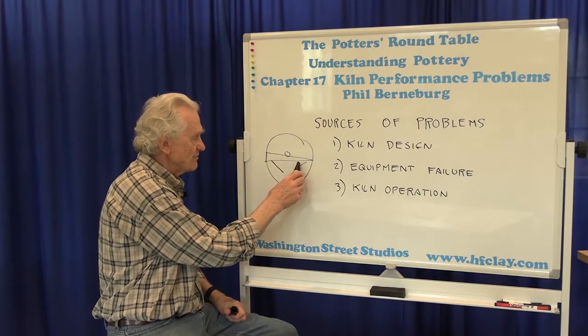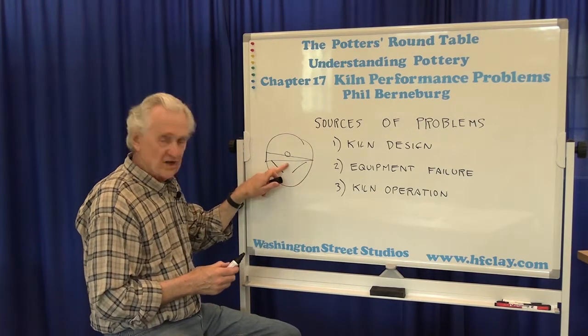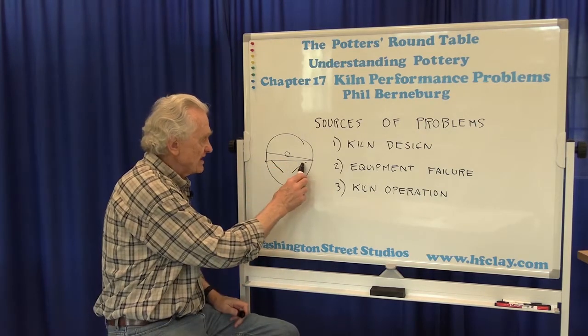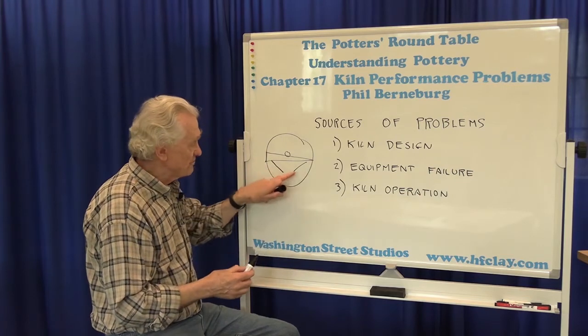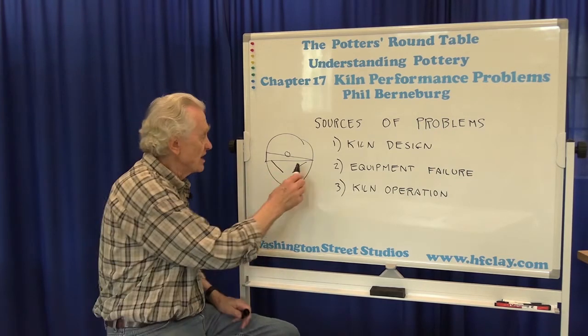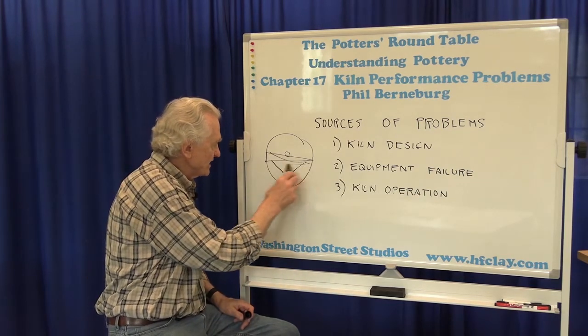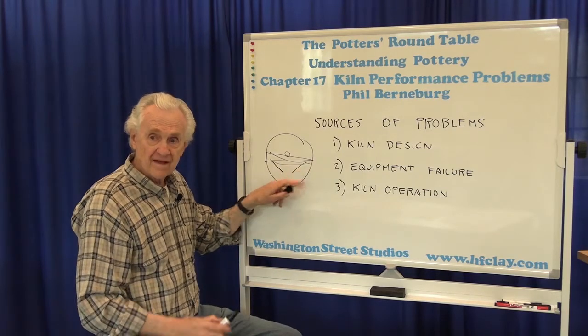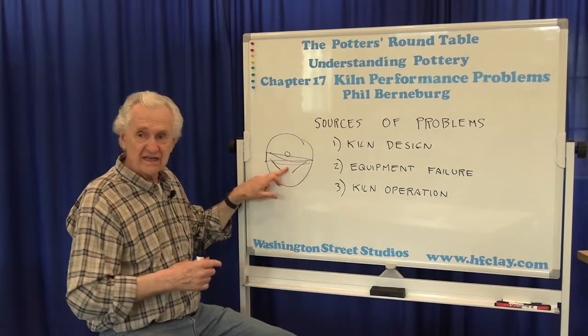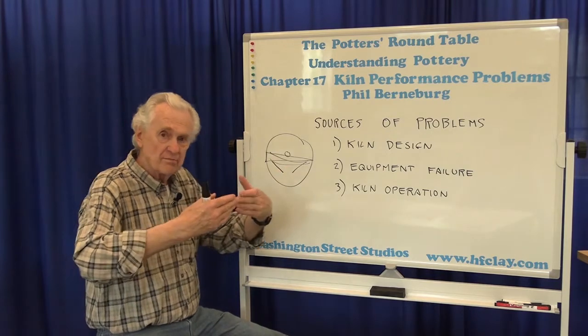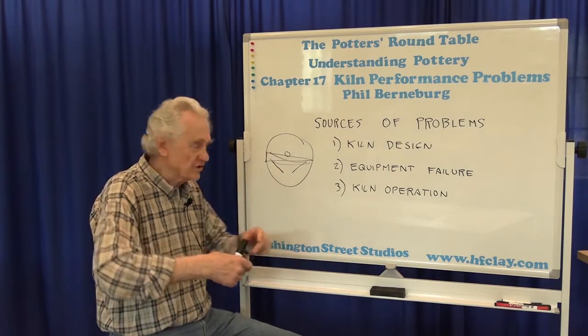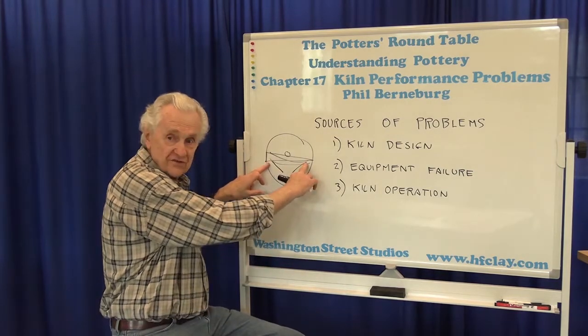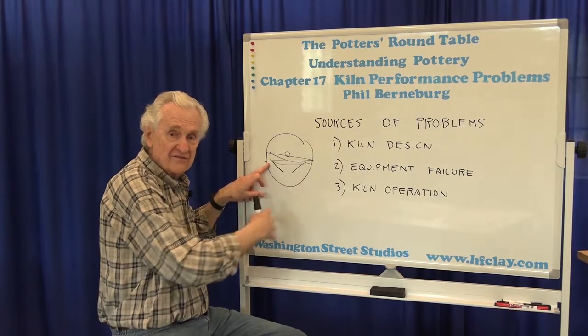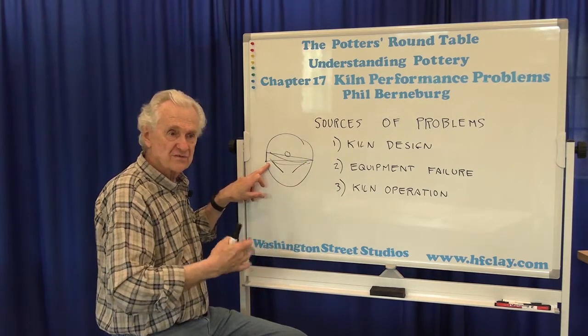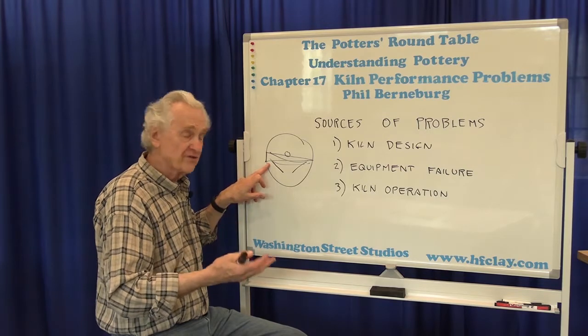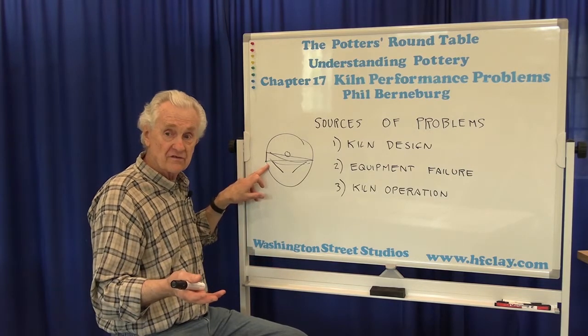Well, one of the things that can happen is sometimes when the cone starts to get soft, and if these metal blades have started to corrode, when it starts to bend, it can actually stick to the metal. And in order to bend completely and trigger the switch, it has to bend down to a certain curvature. And if it sticks when it first starts to bend, it can't bend. It would have to get a lot hotter to the point where it's really soft and it will almost droop under its own weight. Well, by that time, the kiln is overfired.